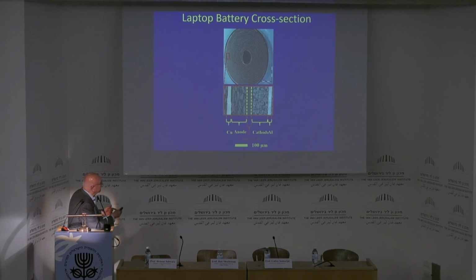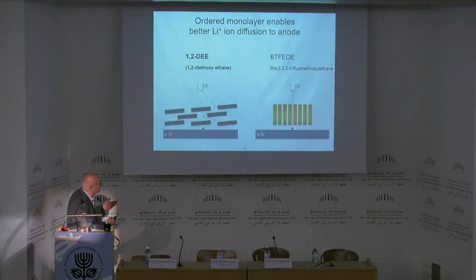Now, it looks like this, and it's a very good catalyst, but it has a finite lifetime because the lithium intercalates both in the anode and the cathode, and as it intercalates, it destroys it. So this has a finite lifetime. But it turns out that if you fluorinate the electrolyte, the organic electrolyte, which is this one here, then it lines up, and it repels the lithium ions, and the lithium ion increases the speed of transition from the anode to the cathode by 2 orders of magnitude. So this is a technology in development, and if you talk to Jonathan Horowitz, he's in Tel Aviv, and he will tell you more than you want to know.